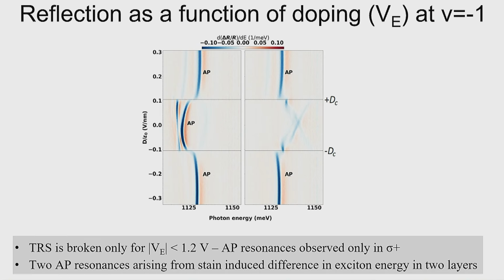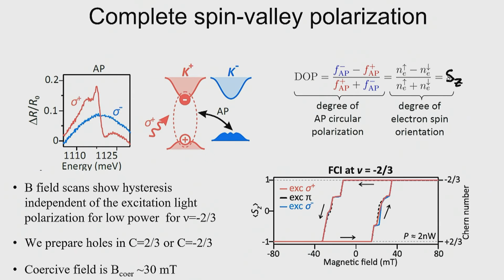We basically go to zero field, and we see that these attractive polaron resonances that I told you about, we only see in one polarization, none in the other. So just like I described to you, this tells us that all the holes in the system are spin polarized. Okay? And this we can then check by essentially tuning the magnetic field and see that as we tune, let's say, the magnetic field down, we can switch the degree of polarization rather abruptly, and there is a nice hysteresis curve which is generic for first order phase transitions or for so-called Ising ferromagnets.